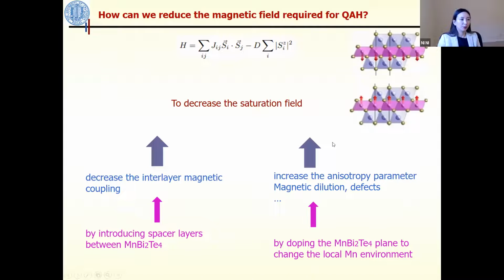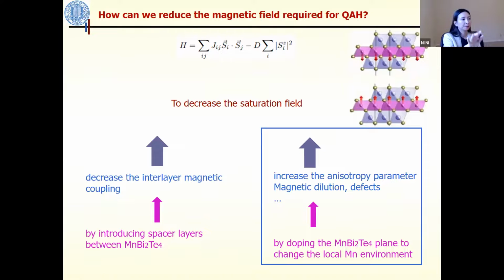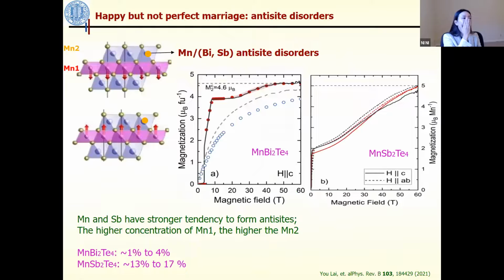As we talked before, this is based on the material design strategy of the second part. Initially, we wanted to dope antimony onto the 124 plane so that we can see how we can change this anisotropy parameter and thereby change the magnetism inside this material. Okay, but before I go further about the antimony doped 124, I want to introduce some background on this so-called antisite disorder. So that's what I said: it's a happy marriage, but it's not a perfect marriage.